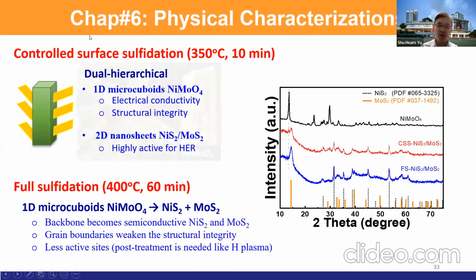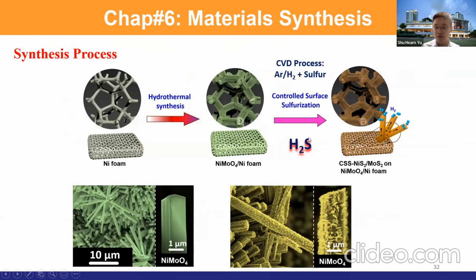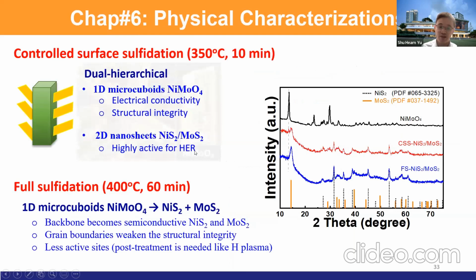So in this case, we have a dual hierarchy structure. We have a 1D microcuboid nickel molybdenum oxide, and then we have our active catalyst, right? We have nickel sulfide and molybdenum sulfide grown on the surface. Because at high temperature, the H2S environment is a reductive environment, this oxide material will reduce. Nickel and molybdenum will reduce to form metals. As they diffuse outwards, they interact with H2S and form nickel sulfide and molybdenum disulfide. These two materials are active for HER.